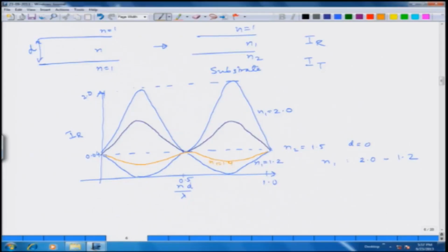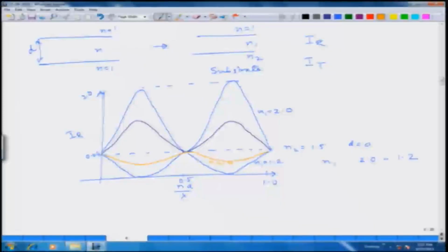This is not surprising, because we know that this interference effect is going to be oscillating with thickness. When you have certain thicknesses where the path differences interfere constructively, you can see that the intensity of the light increases quite a lot, and whenever you have path differences that cancel out with each other, if the refractive index is low, you would also get the lowest intensity.